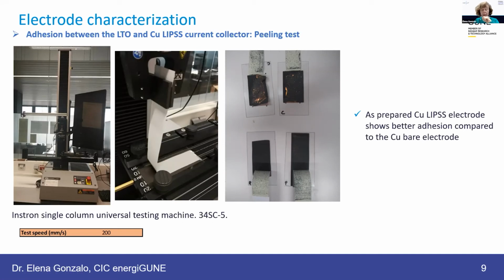And just by eye, you can distinguish that after the peeling test, in those electrodes that were cast on bare copper foil, there are more parts of the electrode that have been detached, so more active material that has been removed. While in the other two cases, with the copper lips, most of the surface is covered after the peeling test with electrode material. So we can say that the as-prepared copper lips electrode shows better adhesion compared to the bare copper electrode.